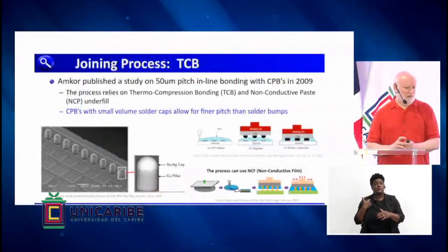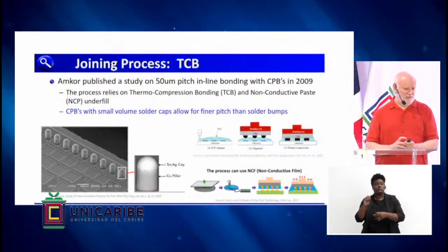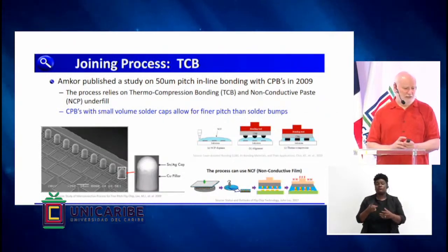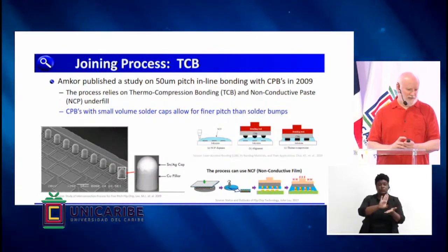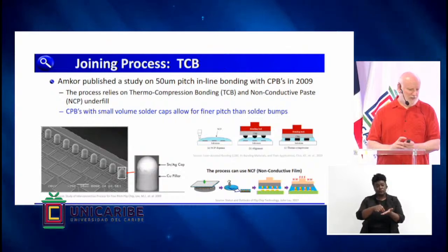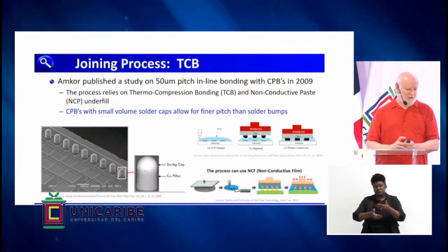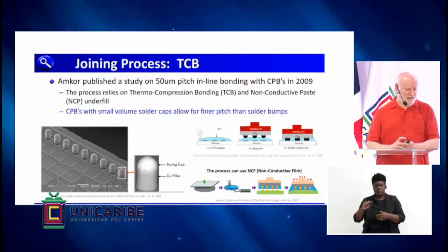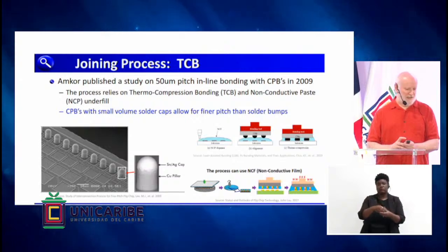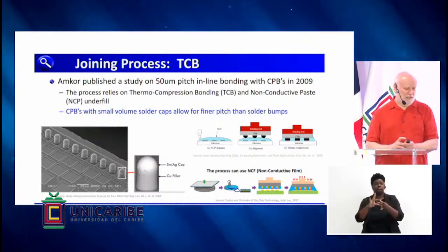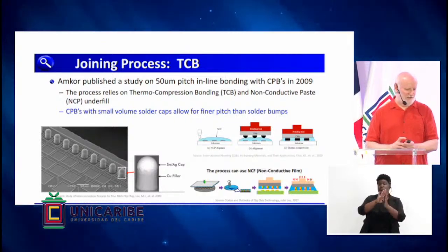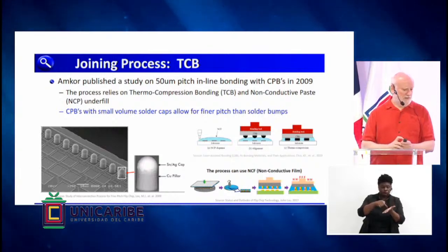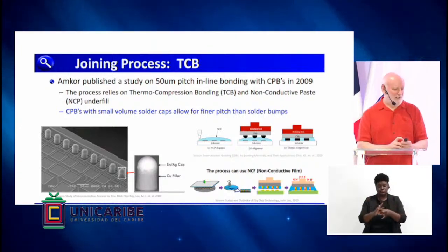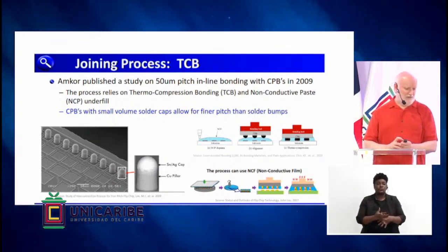So I mentioned that if you go below about 80 micron pitch, we have to go into something we call thermocompression bonding. So this is no longer mass reflow in an oven where you can do many parts at the same time. This is each chip individually is bonded to its substrate. And you can see the process there in the diagrams, where in this case NCP, or non-conductive paste, is being put down, and then the chip is held by a bond head and pushed through that paste onto the bond pads, and the temperature is raised so that the solder reflows, and then the bond head is cooled down. As the solder solidifies, the bond head is removed. So the trade-off here is that now you have a fairly slow process, and you're doing one chip at a time, but you can do finer pitch.